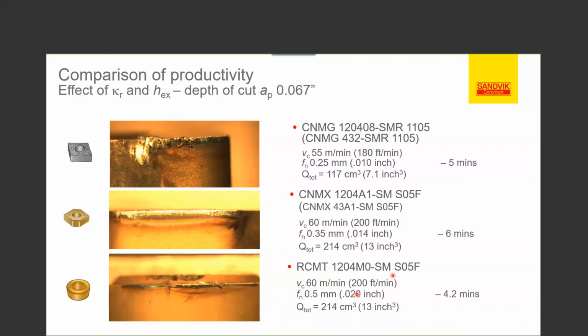And you can see here what happens is we're going from a cubic metal removal rate of about 7 inches on the button or 45-degree entry insert to 13. So we're almost doubling our productivity. And you could see it took us 5 minutes to do this, as opposed to 4 minutes, to double our productivity. So please keep that in mind. Anytime you're using these inserts, we need to take into serious consideration the chip thinning effect, but look at the amount of productivity you're gaining and also process security.